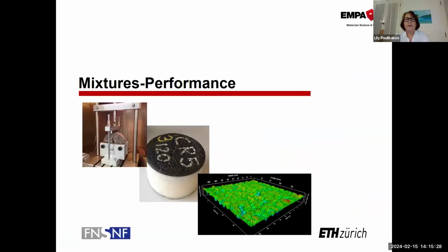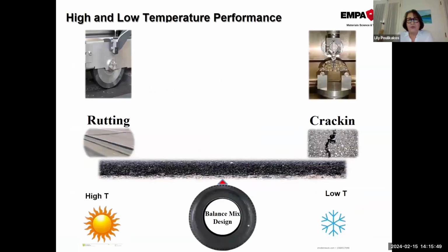Now, moving on to the mixture performance. Here in green, I'm showing you the surface texture. The surface texture is actually very important for the noise performance of the mixtures. I'll show you some results from the various mixtures that we have tested. Again, as I mentioned before, it's very important to look at high and low temperature performance, as these materials might be particularly susceptible to rutting or cracking.